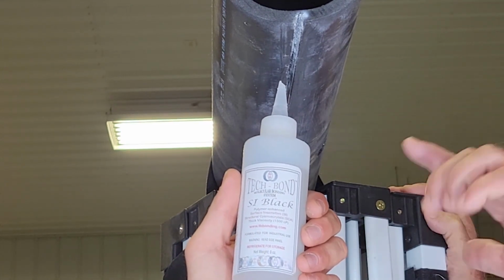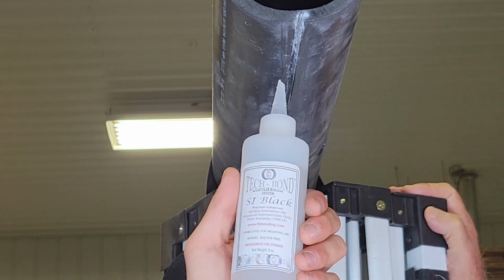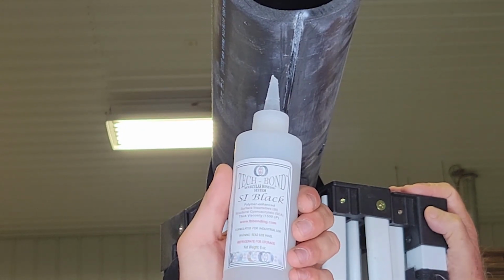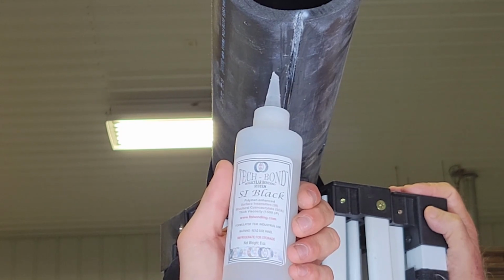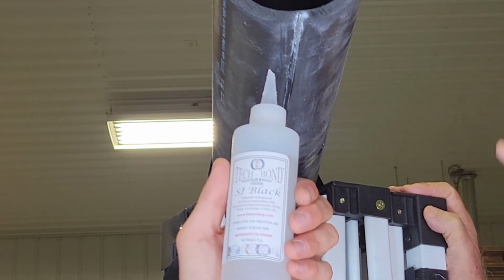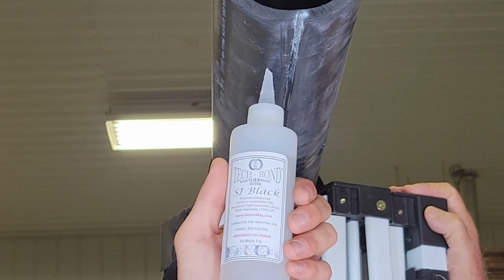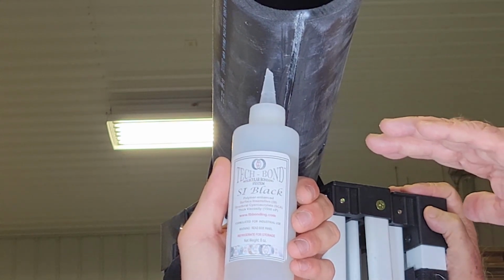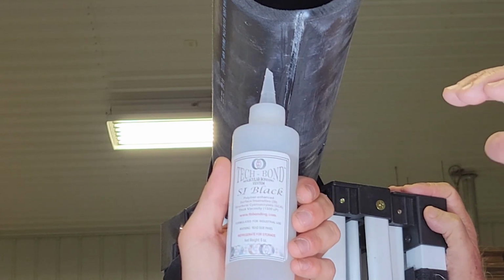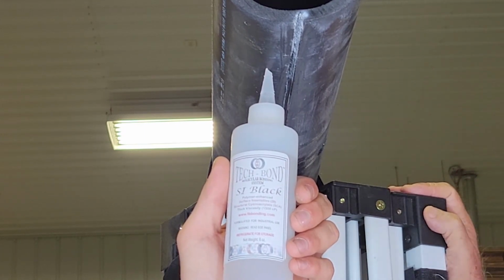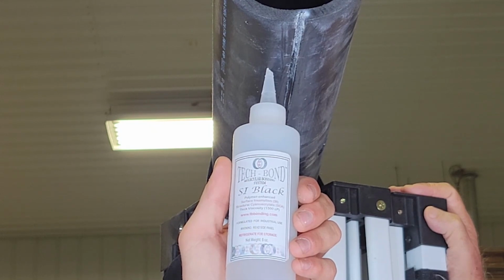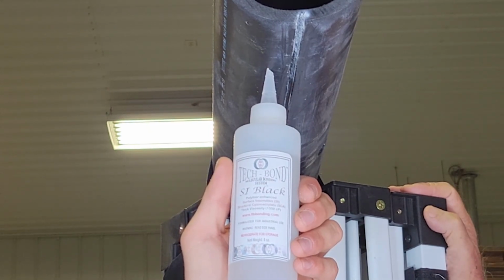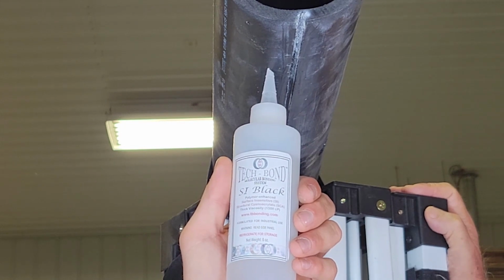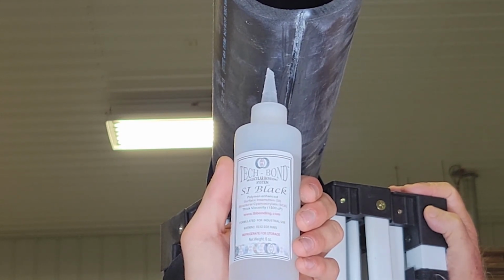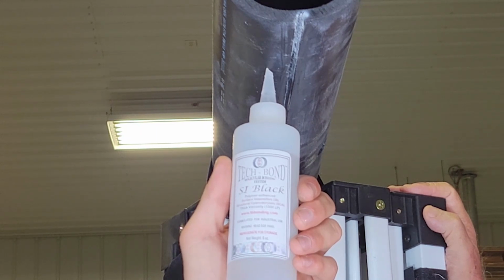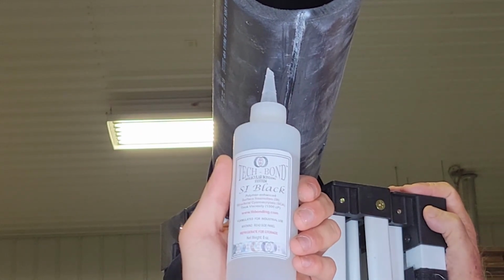Now, we're going to apply the adhesive first. To begin with, on the bottom side, we will use syringes that will be able to get the adhesive well up into the end of the 40 millimeter deep cracks. But for this video, we're going to show how the last few layers of adhesive and filler would be applied. But with the syringe, the adhesive will get up into the crack, and when we go to spraying the polyfiller in, we have a needle point on the end of our sprayer that can get up into the 40 millimeters of the crack.